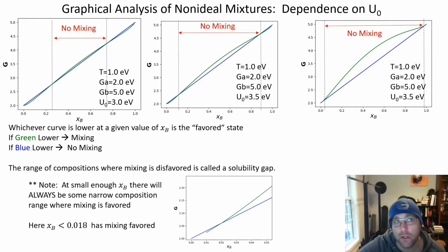And that's actually a really interesting and practical point, because it sort of tells you that if you're making a new material in the lab, the idea that you can have absolute purity in your material is nonsense, right? Because there's always a thermodynamic driving force to have a very small amount of impurities. And so the thermodynamics of creating a pure material is almost inconceivable in a real lab situation where you do have potential for very small quantities of impurities. They will come in almost guaranteed.